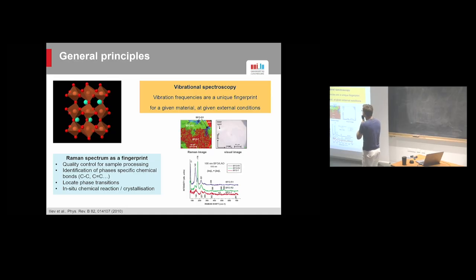I mean, it's just one example where you do a Raman map and you measure your spectrum. Here, every single peak corresponds to a phonon mode, and you recognize the signature of the R phase and the signature of the T phase, and you produce this beautiful Raman map that tells you something about the results of your growth, okay? So it's extremely useful, but very much a fingerprint approach.